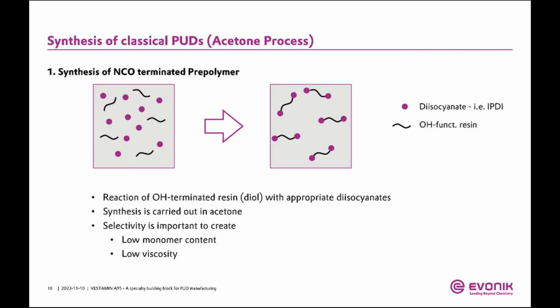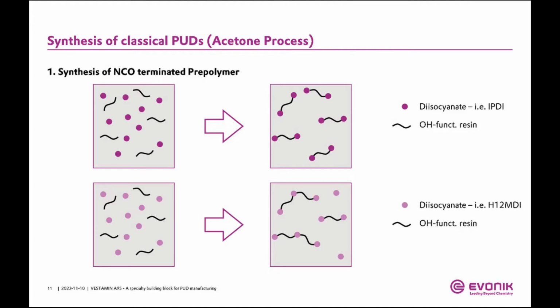In many cases, I would say the diisocyanate of choice you use here is the IPDI we have just introduced in the isophorone chain, but you can also use other isocyanates. For instance, we have here another one, which is the H12MDI. And the difference between these isocyanates is their selectivity. IPDI has two differently reactive NCO groups, so you can very easily achieve this ideal picture of the 2-to-1 stoichiometry of your prepolymers, whereas when you have an unselective isocyanate like the H12MDI, you get more and more chain elongation, which then increases your viscosity.